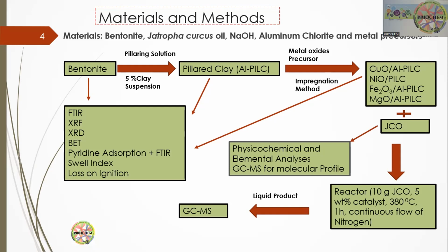Then the metal oxides were doped onto the aluminum pillared clay using the impregnation method, and we prepared it in such a way that it will give us 20% metal oxide on aluminum pillared clay. The bentonite, the prepared pillared clay, and the metal oxide doped on aluminum pillared clay were all characterized using FTIR, XRF, XRD, BET, pyridine adsorption, and in some cases their swelling index and loss on ignition. Also, the Jatropha curcas oil before the reaction was subjected to GCMS analysis for the molecular profile, physicochemical analysis, and elemental analysis. And then each